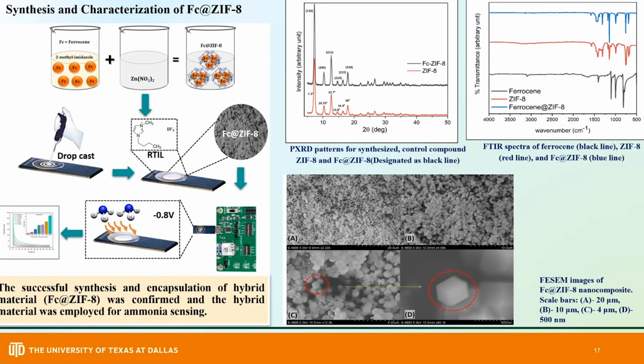The synthesis scheme involved synthesis of the ferrocene@ZIF-8 composite, which was drop casted onto the working electrode surface of the sensor. Then RTIL was used as an electrolyte to allow diffusion of the ammonia gas onto the electrode-electrolyte interface and cause a change in current and show a dose-dependent response. The successful synthesis and encapsulation of the hybrid material was confirmed, and then that was further employed for ammonia sensing.